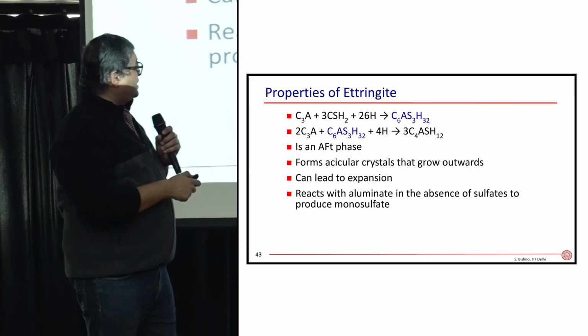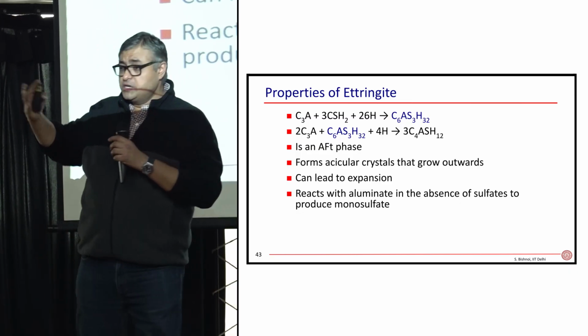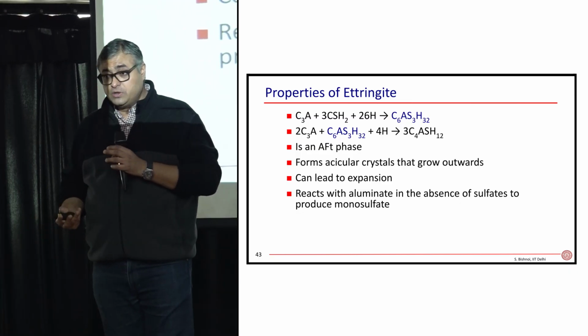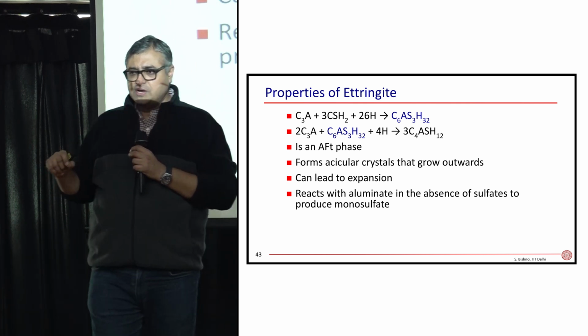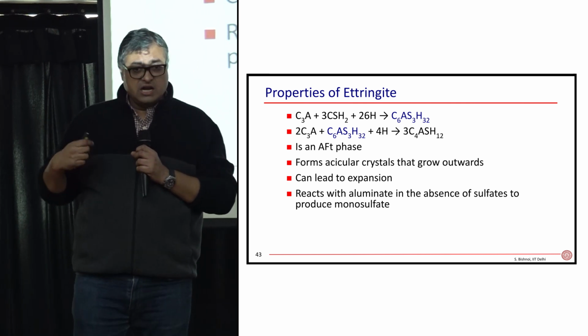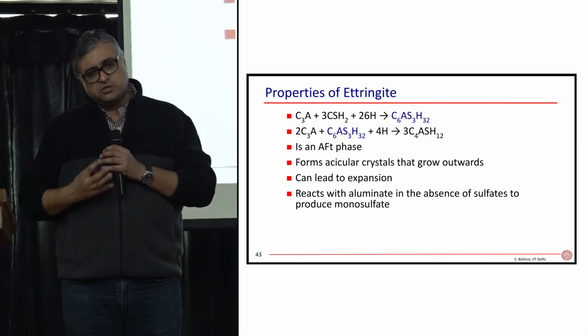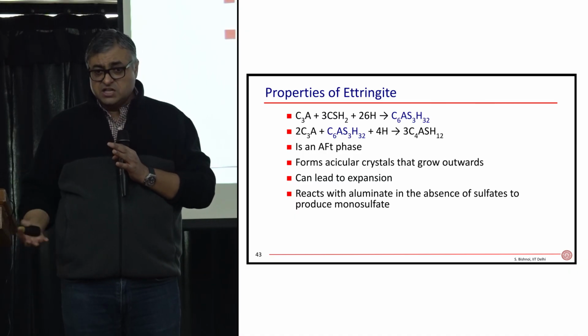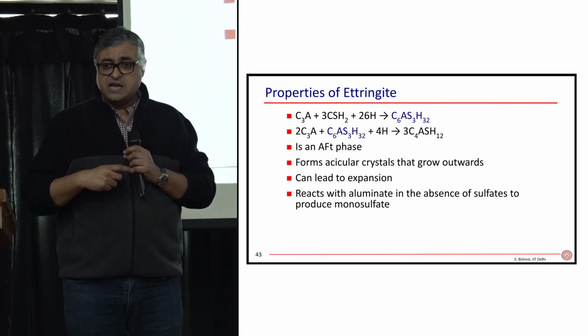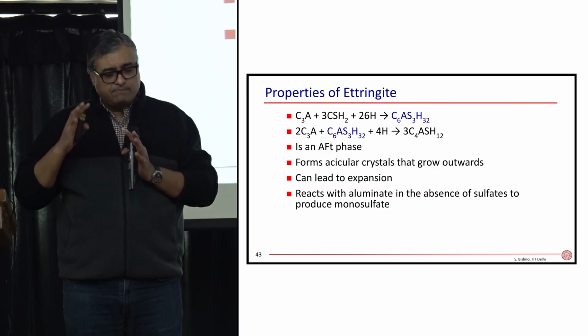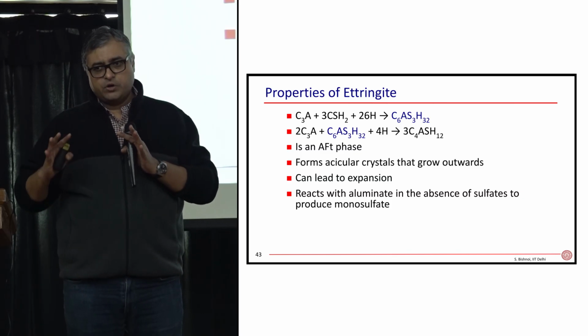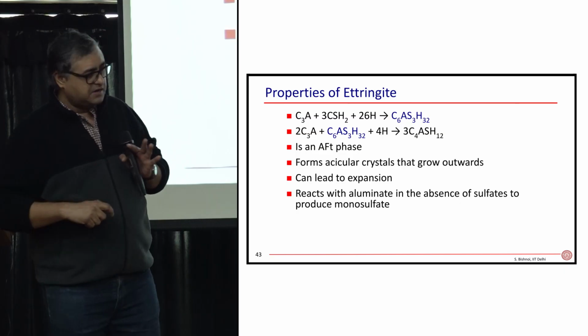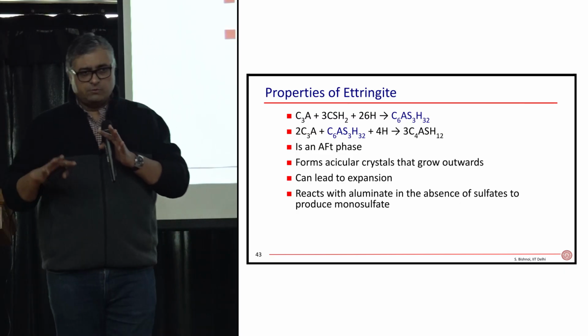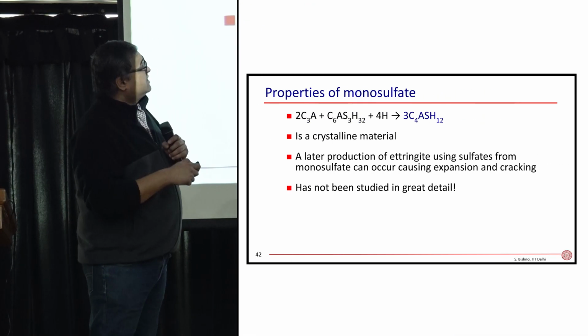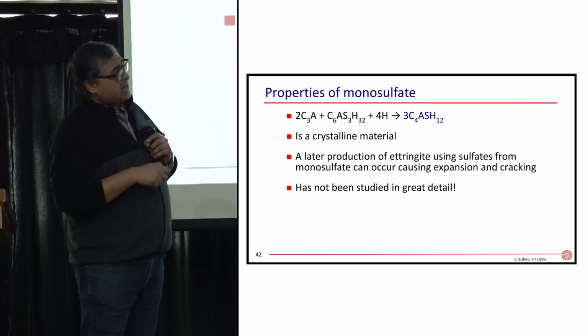But then, if this ettringite forms in the long term, it can lead to expansion, it can lead to cracking. But in the beginning, this ettringite forms needles that do not lead to cracking, that do not lead to expansion, because there's plenty of space for these crystals to grow. And eventually, in Portland cement - I'm putting that caveat because it's more complicated than that - eventually in Portland cement, when gypsum runs out, this ettringite is going to get converted into monosulfate.